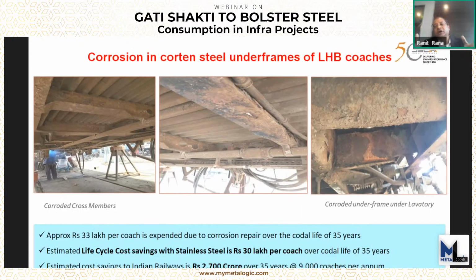Similarly, in coaches also, if you look at the current fleet of LHB coaches, the entire shell is made out of stainless steel. But there is, Ranit, requesting you to please finish in 2 minutes. Yeah. So if you look at the underframe, it is still in carbon steel, and it also undergoes significant corrosion. So RDSO had suggested a stainless steel grade 201 LN, which if used will result in a savings of almost 30 lakhs per coach over the codal life of 35 years.